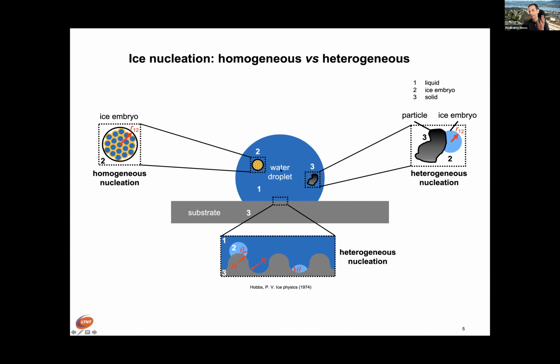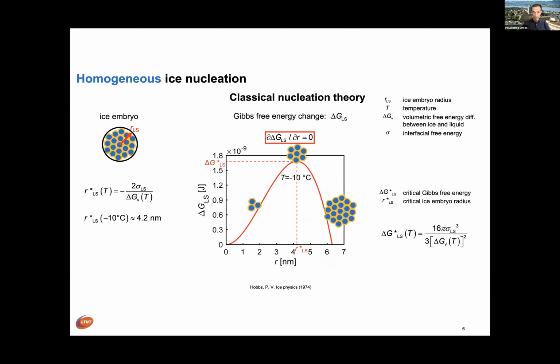Now, these embryos do not have an easy life. When they come to life and start appearing, they're very small in size, and as you can see in this very simple energy-size diagram, their growth is not favorable. If they try to grow, they have to go up the energy barrier and overcome it. But as they keep growing, and as a function of time statistically, you start having embryos that grow fast enough, reach a critical size that I show here, and then from that point on, the growth is favorable, toward decreasing energy, and it occurs actually explosively, extremely fast.